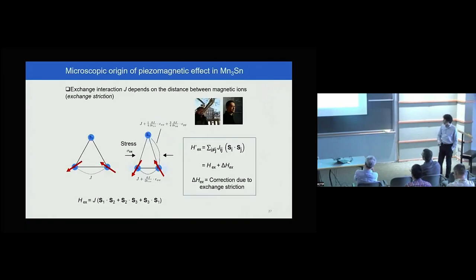so what is the mechanism behind this? Oleg and Sayak, former student of Oleg at JHU, have made a lot of extensive investigation on this mechanism and found various things, and one of them is exchange striction, which has turned out to be quite important. And of course, exchange striction is that the superexchange depends on the distance. This is so simple. And when this antiferromagnet is frustrated, like 120 degree order, if you bring these manganese, for example, closer to each other, antiferromagnetic correlation develops, right? It becomes stronger. Vice versa.